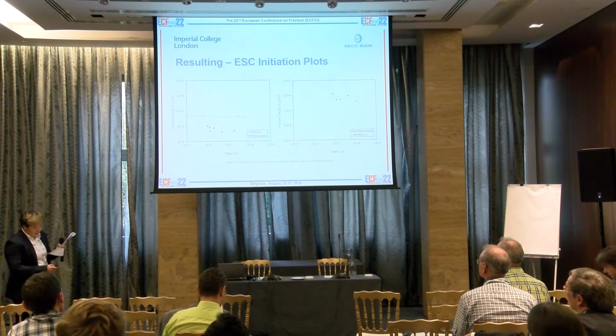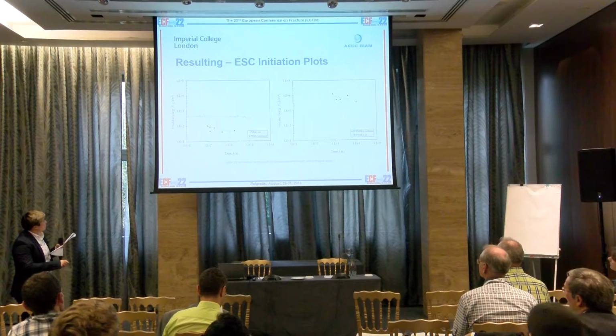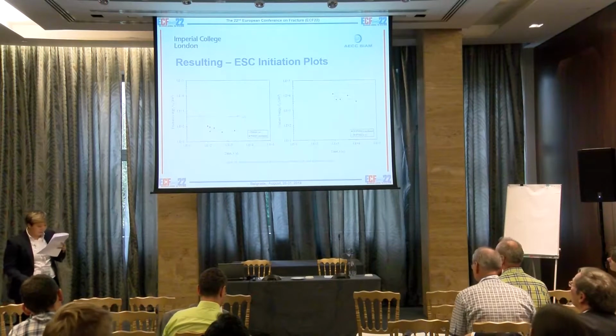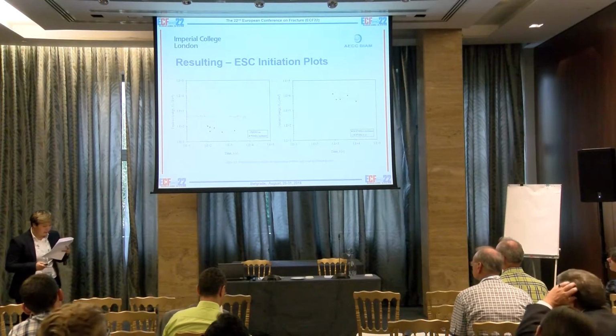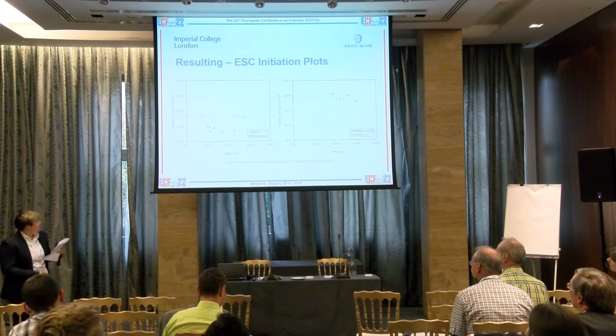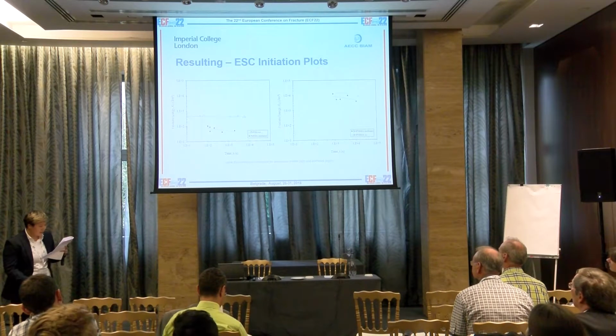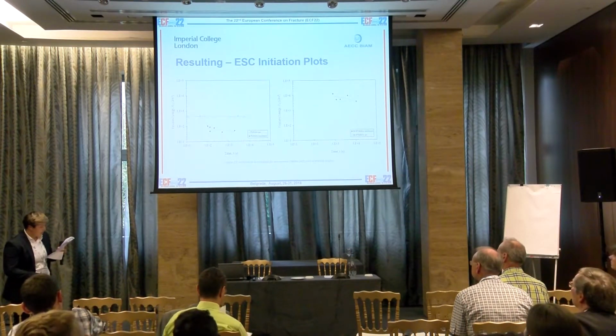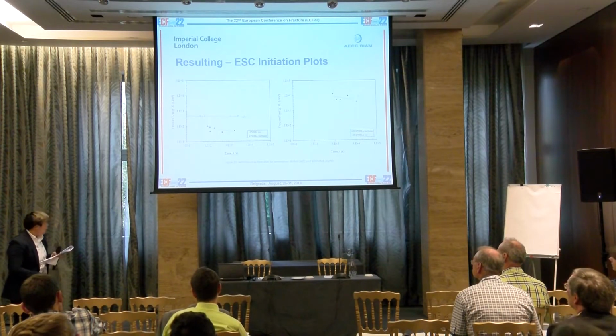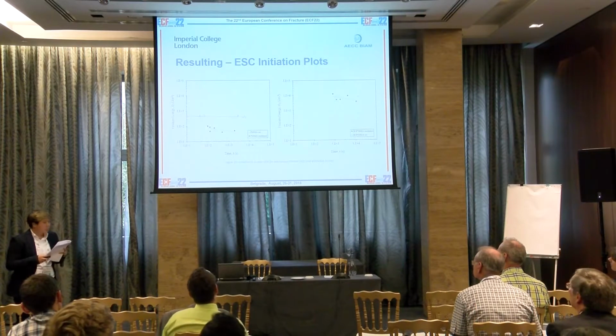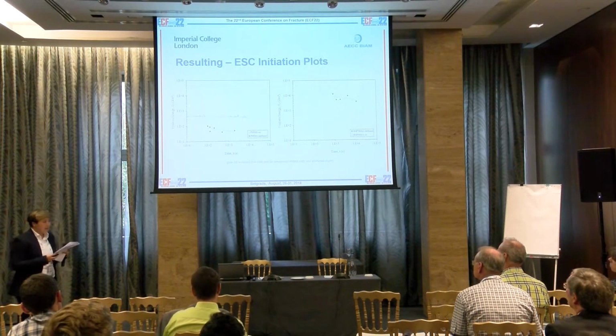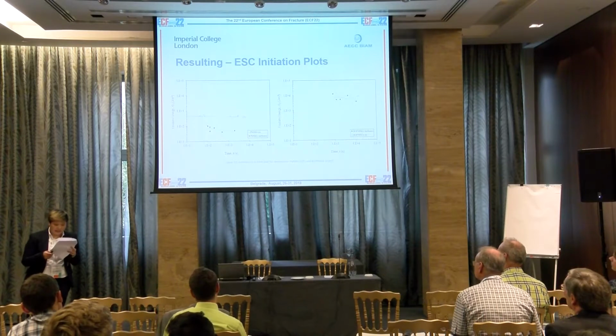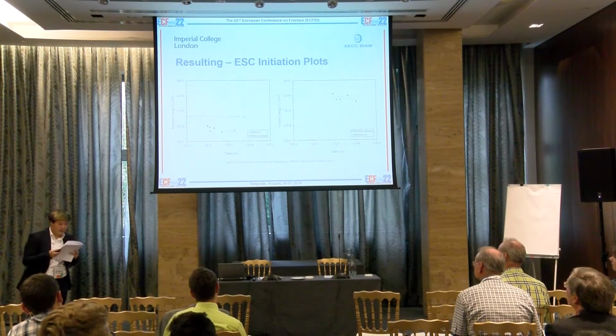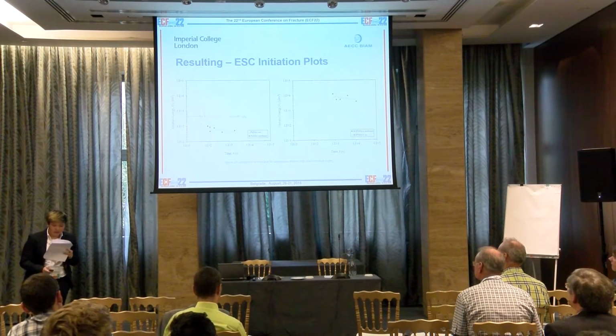The intersection of the in-air and in-environment curves represents the value of critical initiation time and the corresponding fracture energy. Overall, at least 5 repeats were performed on both materials under each environment, except for the case of biaxial orientated PMMA in air. Only one complete set of data was obtained, as the material has a high ESC resistance, and often the crack does not propagate through under constant load.